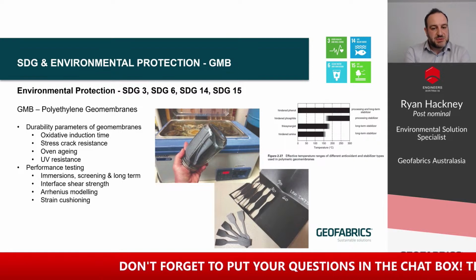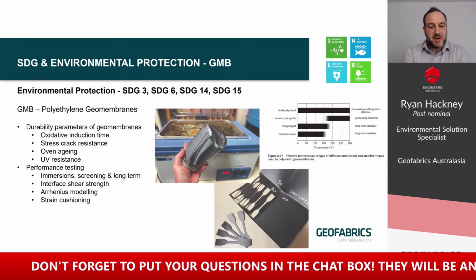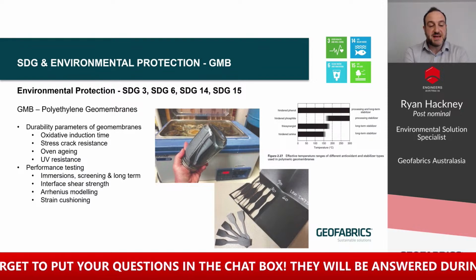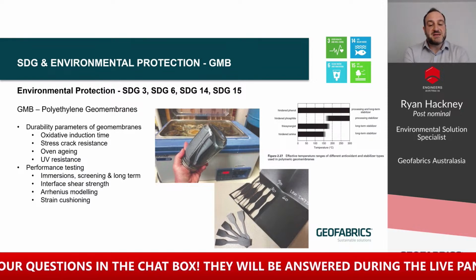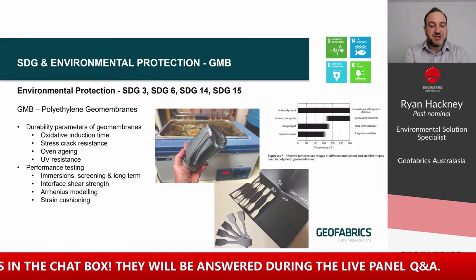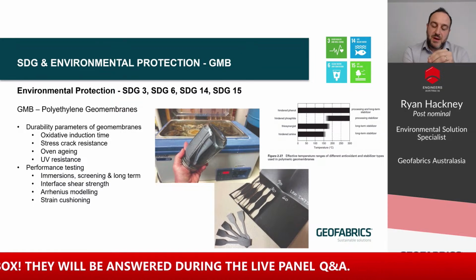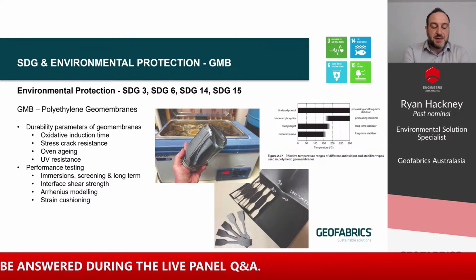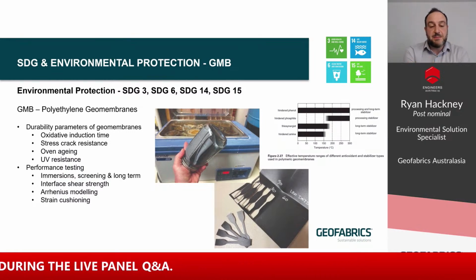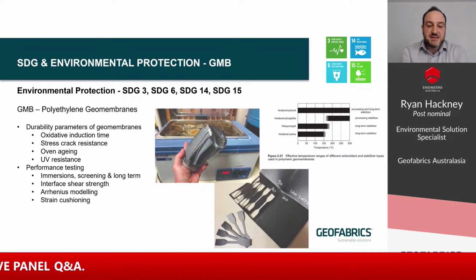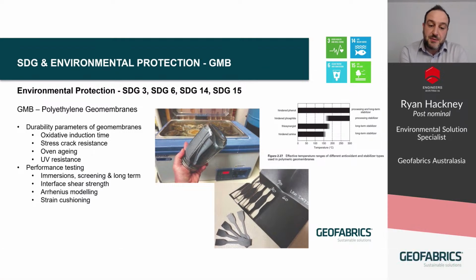In terms of measuring the performance of geomembranes, similar to what I demonstrated with GCLs, we perform what's called an immersion test. We take the chemistry from the site, the leachate or the liquor or the pore water, and we immerse the geomembrane in that actual liquid. We do that at elevated temperatures, which accelerates degradation reactions. Typically what's happening is the chemistry is reacting with those stabilizers and antioxidants, which are protecting that base resin from breaking down.